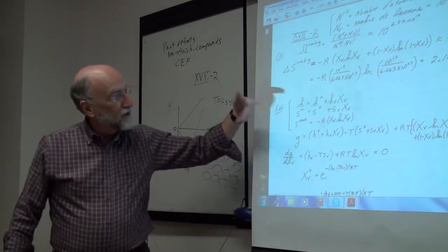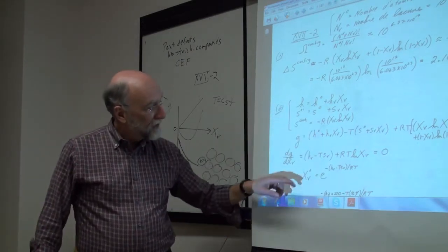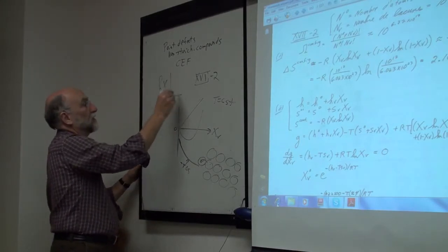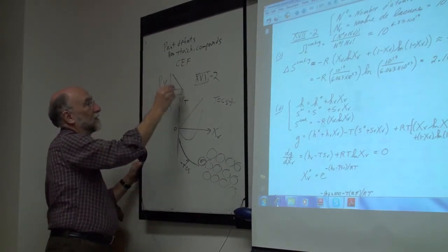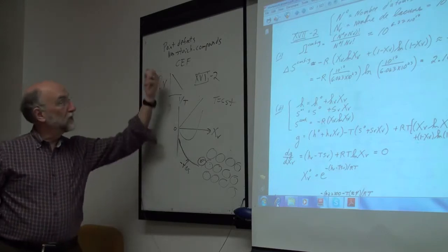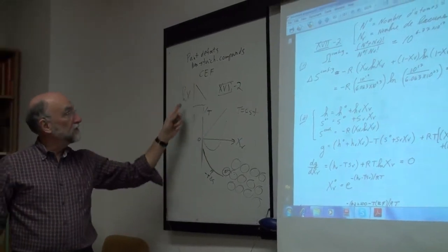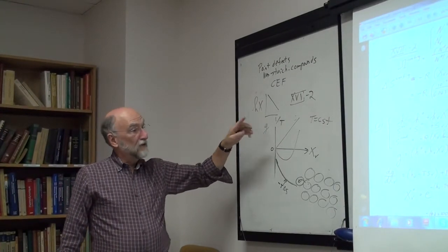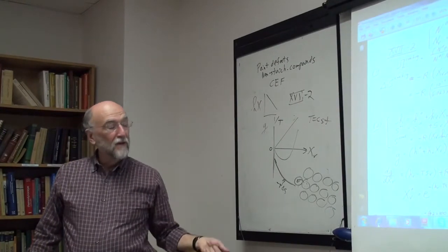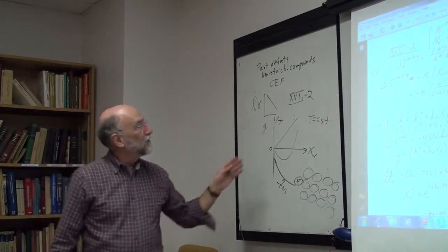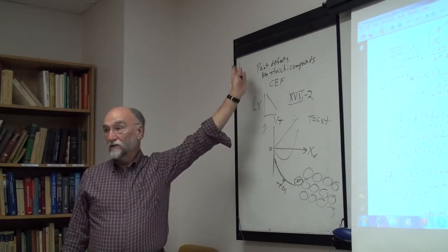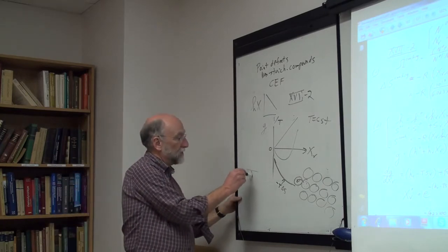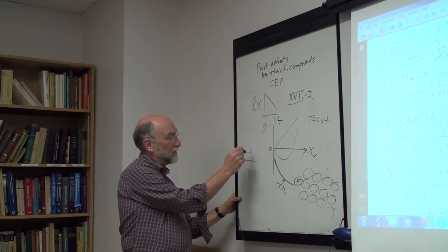Okay, when you do that sort of thing, you have a thermally activated process, then you always get this log X versus 1 over T. So it's an exponential thing with 1 over T. As you increase the T, the number of vacancies goes up exponentially. Since the diffusion coefficient depends on the number of vacancies, the log diffusion coefficient also goes up that way.